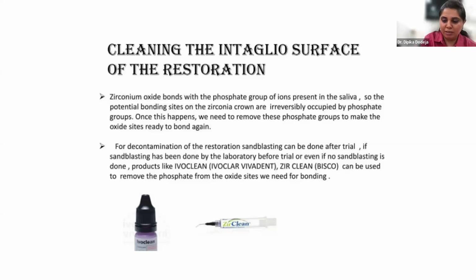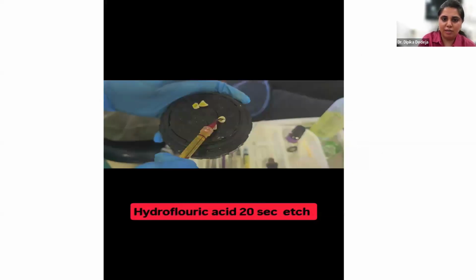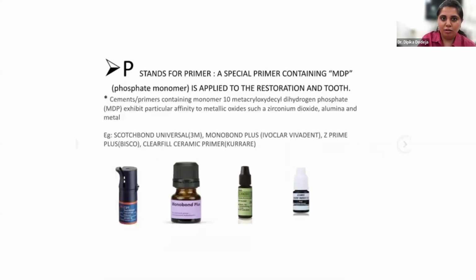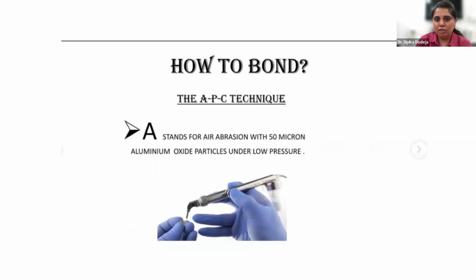So to help us do that, we have zirconia cleaning agents like IvoClean from Ivoclar and Zirclean from Bisco. You can apply these for like 30 to 40 seconds, agitate it and rinse it. So this is a very important step in zirconia bonding. You do the trial, clean the intaglio surface with either IvoClean or Zirclean. Studies have shown you can use sodium hypochlorite also, but I'm not sure about it.